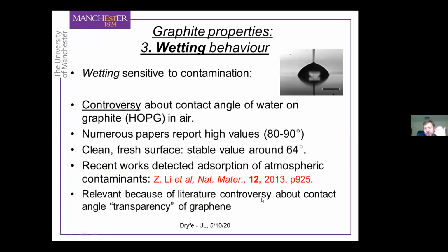And this area has become relevant and topical for another reason. That's because people were interested in the contact angle of graphene. And a big question arose, which was, if you put a water droplet on graphene, to what extent is the contact angle of the water dictated by the graphene, and to what extent is it dictated by the substrate underneath the graphene, i.e. to what extent is graphene transparent with respect to contact angle? And this has been quite a hotly debated area, but unsurprisingly, people could only understand the contact angle of graphene once they'd understood the contact angle of graphite.